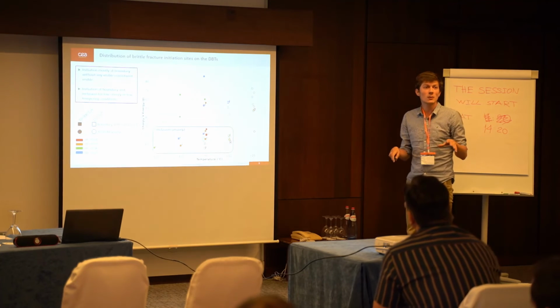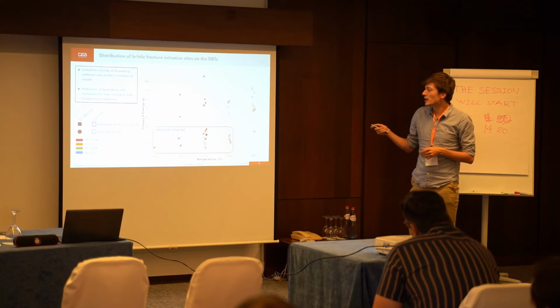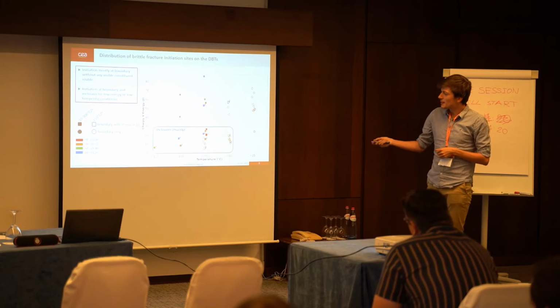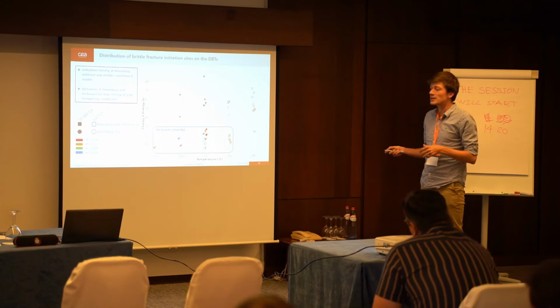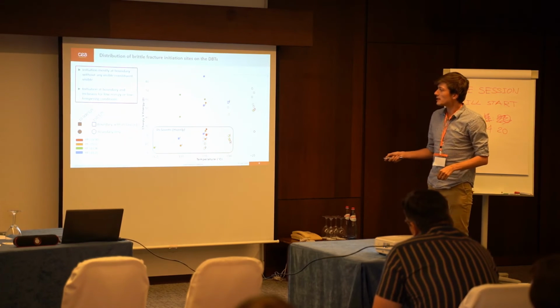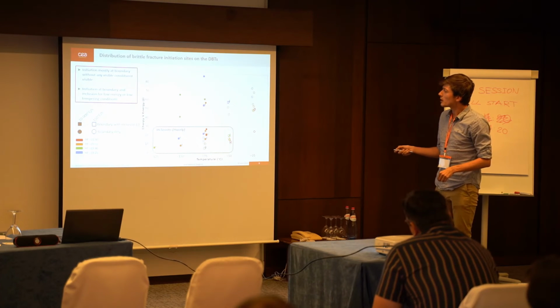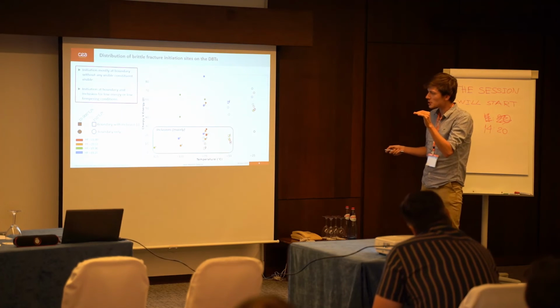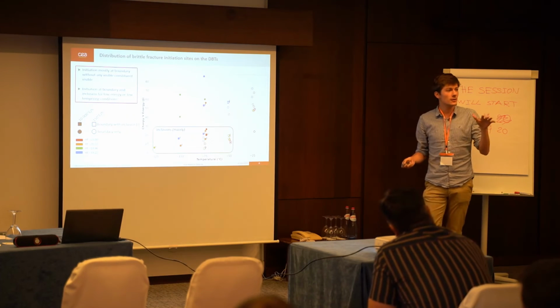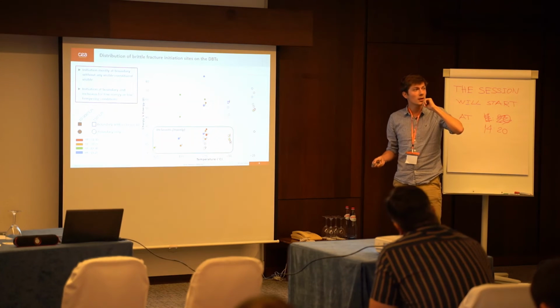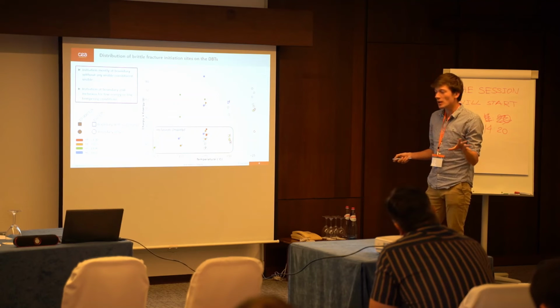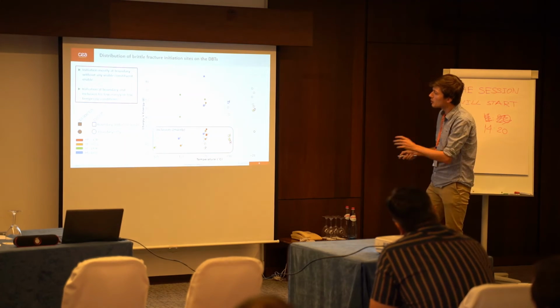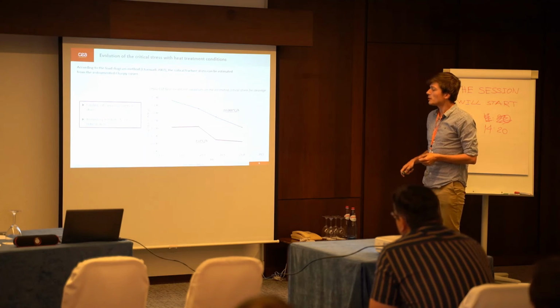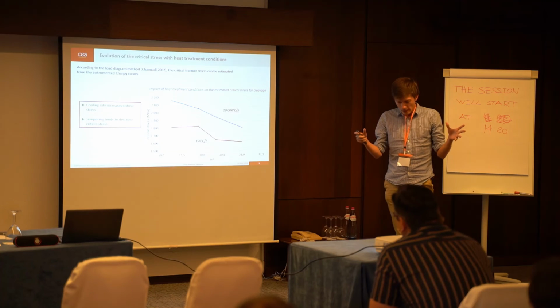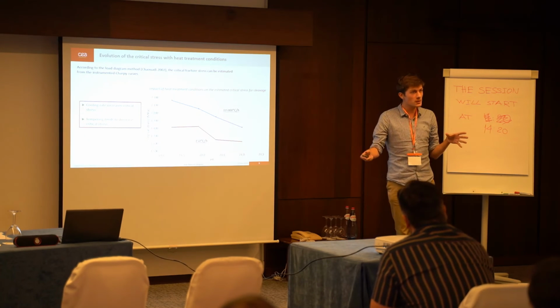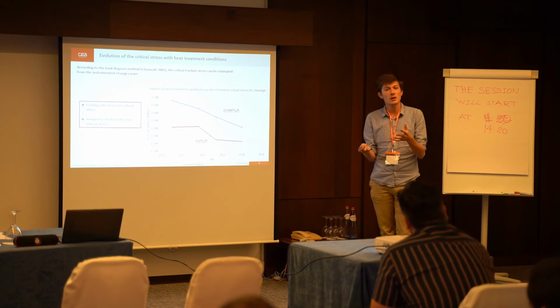We can also have a look at the distribution of the types of initiation regarding the impact test parameters. If you take a look at the initiation on facet border with inclusion, you see that they are mostly localized at low energy configuration. You have some rare cases where it happens at higher energy, but it's always for the material with the less intense tempering, so with a higher yield strength. For the initiation on boundary only, or with the presence of carbides, it happens on all the range of energy and temperature. So we have a very different impact toughness behavior between the materials, yet we have the same initiation mechanism for all materials.